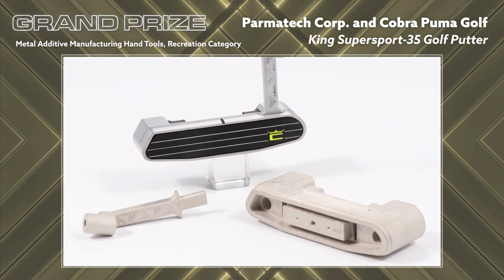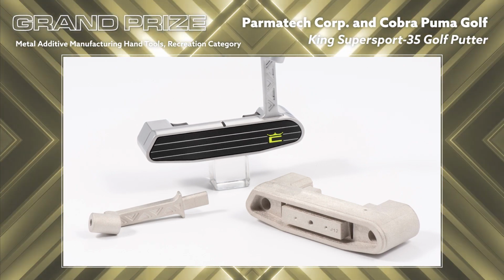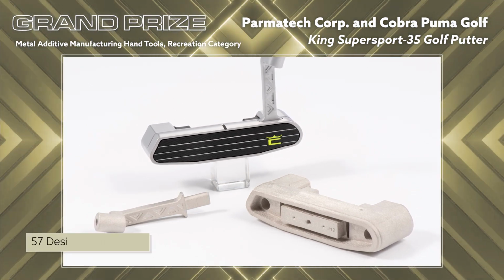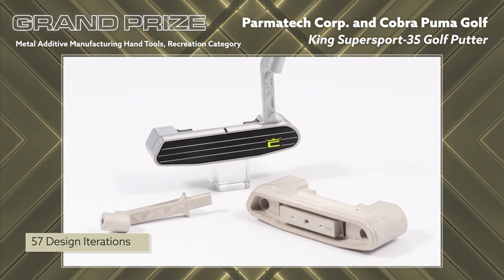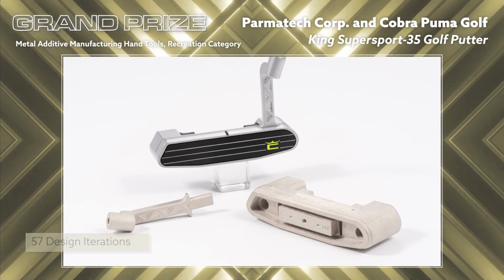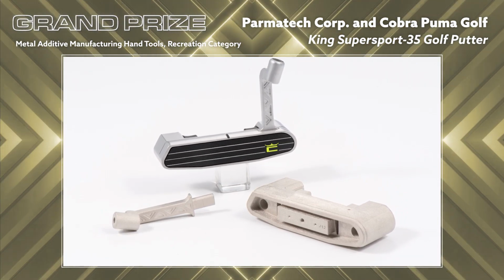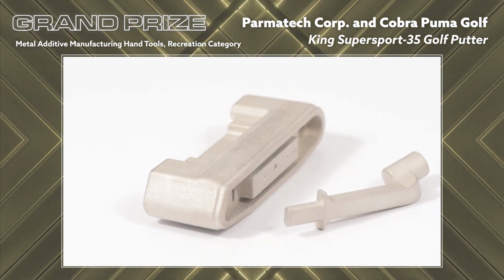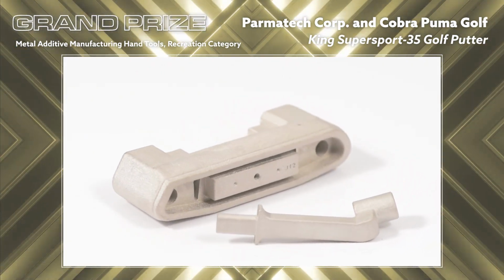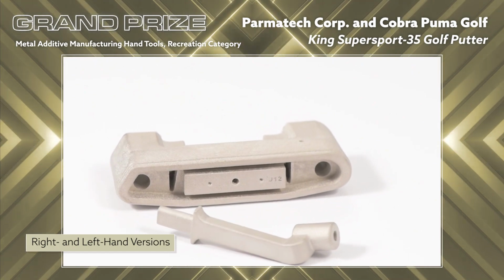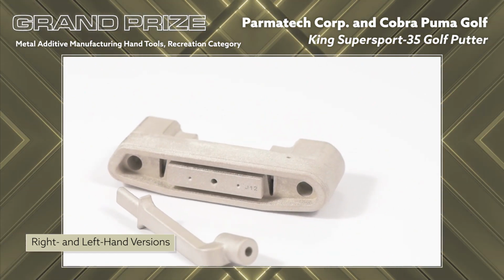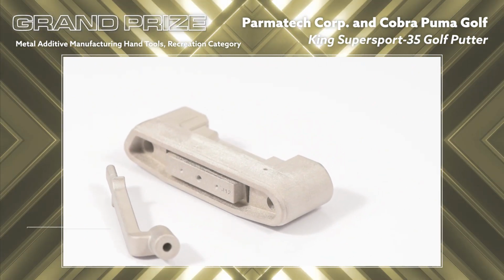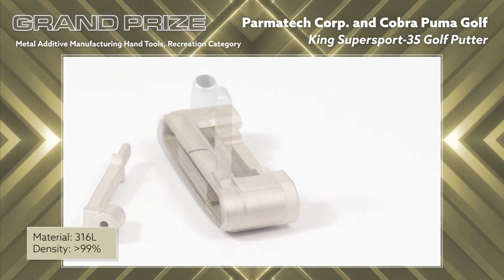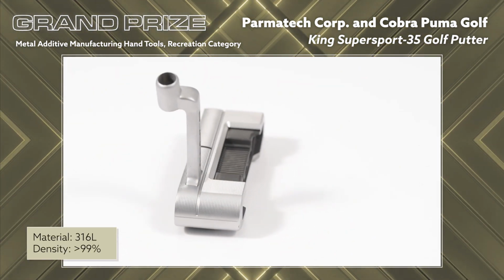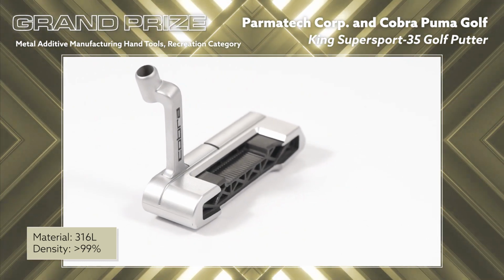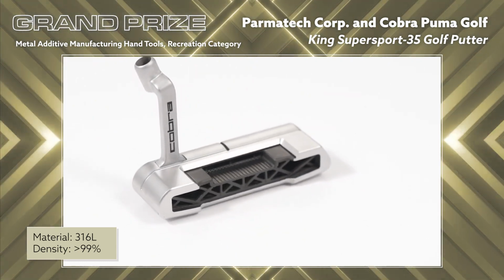The use of AM processing also allowed the rapid design, review, and testing of 57 design iterations, permitting the customer to test the characteristics of sound and feel important to golfers when striking a ball, but not easily simulated in design software. The flexibility also allowed production of both right and left-hand versions of the putter head and hosel without the need for tooling changes. The parts are made using 316L stainless steel. The strict cosmetic polishing, PVD coating, and milling requirements could only be met by achieving a relative density of greater than 99%.